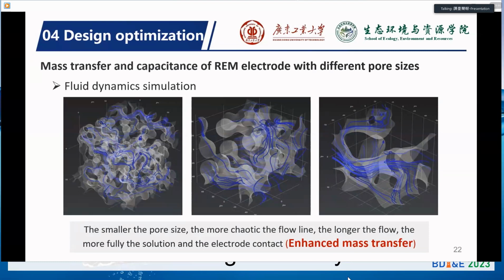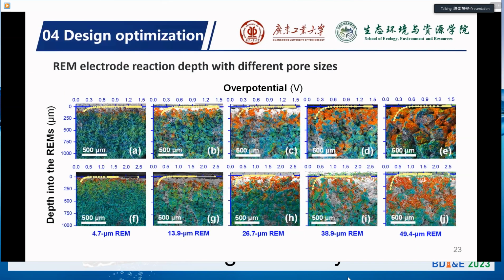So we first used a CFD method to simulate the water flow inside the REMs. This part of the work was collaborated with Dr. Hongjian Zhou. Indeed, the REMs we prepared present the enhanced mass transfer at a small pore size, so this is correct. But when we used numerical modeling to increase the pore size, the reaction depth increased, as shown in this slide.